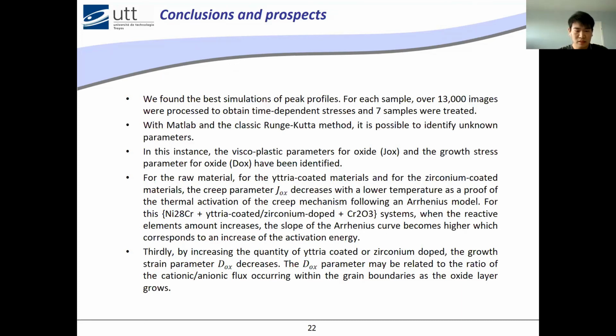In this instance, the viscoplastic parameters for oxide and the growth stress parameters for oxide have been identified. For the raw material, the yttria-coated material and the zirconium-coated material, the creep parameter Jox decreases with a lower temperature, as proof of thermal activation of the creep mechanism following an Arrhenius model.